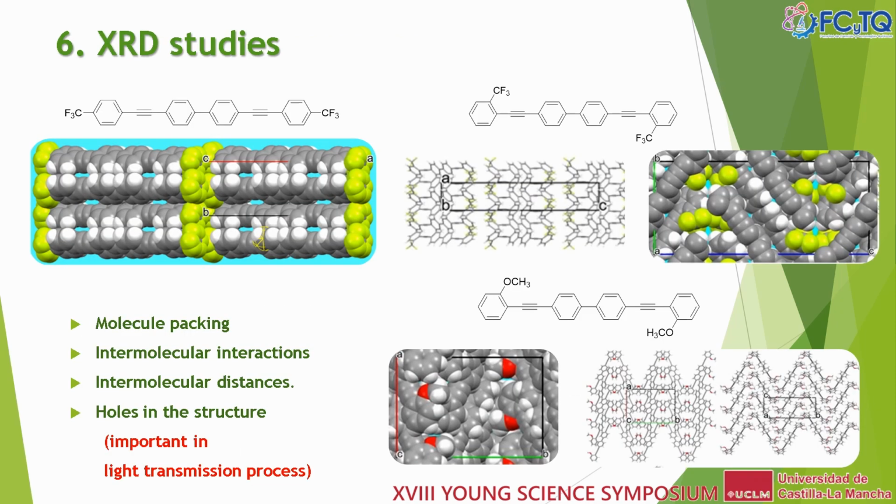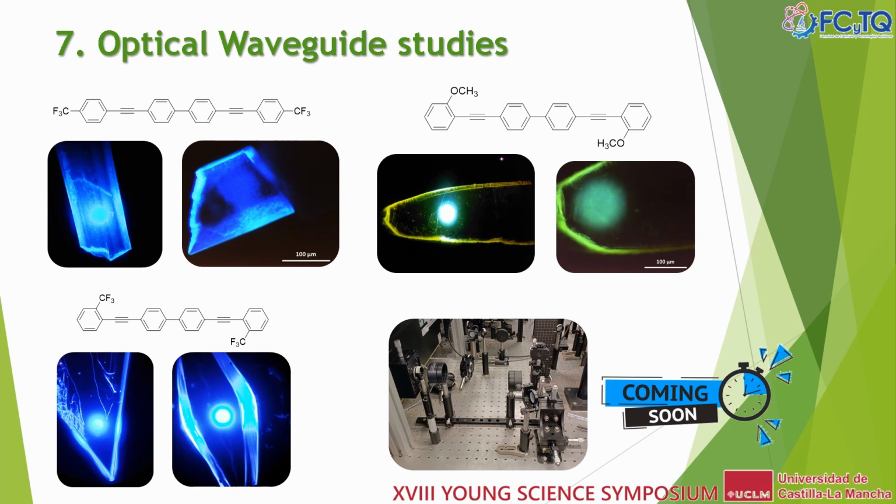SEM provided information of the morphology of the aggregates, and XRD provided the structural information of the crystal, such as molecule packing, intermolecular interactions, and distances. Then, confocal studies were performed, showing that the obtained aggregates had bidimensional waveguide behavior, which are very promising results for their implementation. However, optical loss studies are being carried out to quantify how good light guidance is in the crystals.